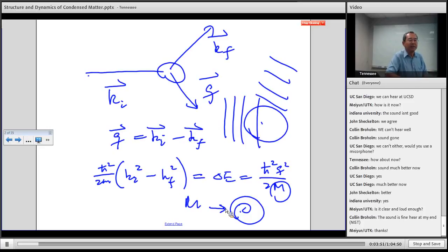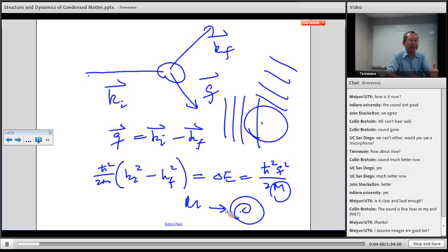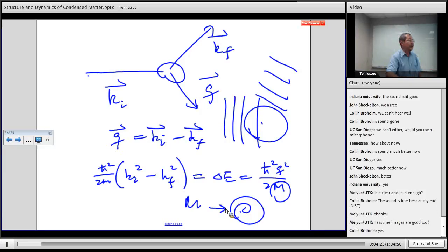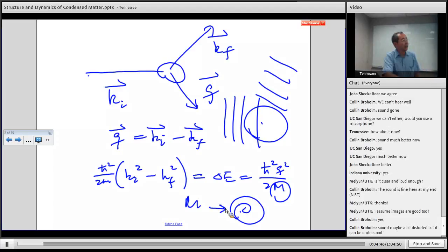The usual resolution of a triple axis system is like 1 millielectronvolt. We will get into the triple axis system later on; Colin introduced this concept a little bit. In diffraction, we use a double axis, but as we discuss later on, if the energy transfer is too big, then the assignment of momentum transfer Q becomes questionable. Essentially, if a system is small, we have a problem. Later on, we'll discuss a correction to this effect, the so-called Placzek correction, maybe next month, when we discuss the local structure problem. You think you're doing an elastic scattering measurement, but some of the intensity you measure is inelastic, so you have to make a correction.